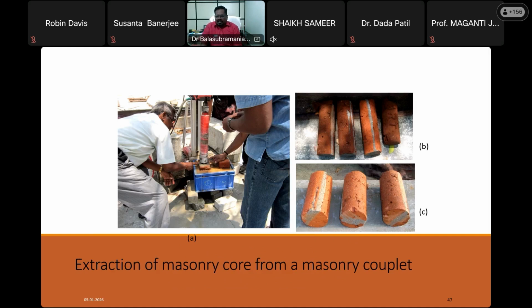The next one is a split tension test. This is a relatively new kind of test. People have been using diagonal tension on wallet specimens, so this is an alternate to that. Here we fabricated the couplet specimens, and then we extracted the core of the bed joint in between, and then trimmed those cores. Figure A shows extracting of the core. Figure B is the extracted core, which is a longer one, and then we trim the ends so that the aspect ratio is 2, that is, length of the specimen to diameter of the specimen is 2.